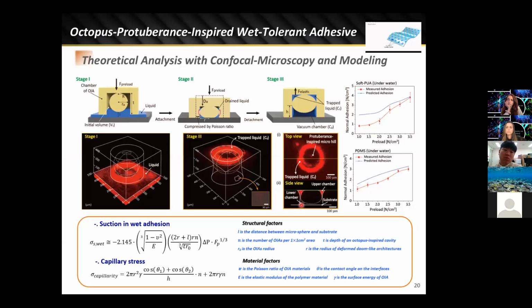Through fluorescent confocal microscopy, we could observe the behavior of water molecules before and after applying preload. As a result, we demonstrated that the lower chamber is induced to a vacuum-like state by observing the trapped water inside the upper chambers.